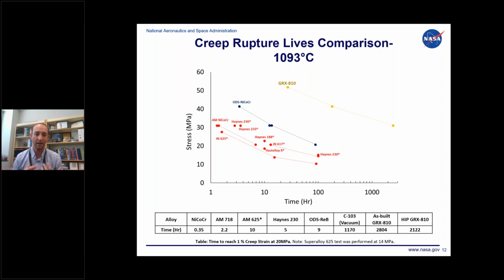If we look at time to get to 1% strain, you're really reduced on the amount of time these alloys are able to operate. 2 hours for 718, 5 hours for Haynes 230, and even our original ODS was 9 hours. But if we look at the as-built GRX-810, it was 2,800 hours.